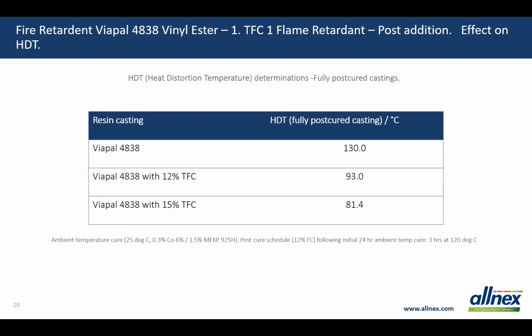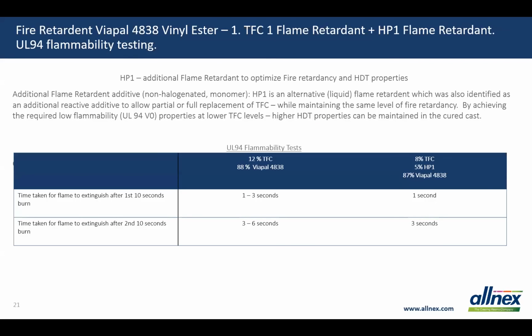So heat deflection temperature is a fairly critical property in terms of things like heat resistance. So we needed to look at other ways of altering that. And one way was to look at synergistic additives or other flame retardants in combination with the initial TFC additive. We tried another synergist that was suggested, an industry recommended synergist. It didn't work. We've tried a few options. However, one particular reactive non-halogenated flame retardant, which we'll call HP1 here, did actually allow us to reduce the TFC level in the formulation.